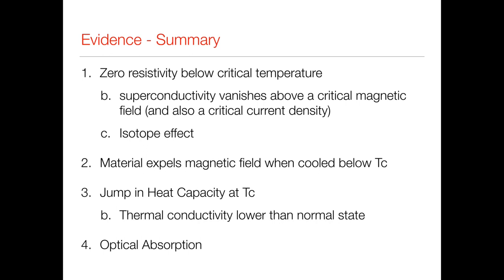A pretty telling piece of evidence is the isotope effect, the fact that the mass of the atoms seems to affect the transition temperature. We've got the Meissner effect, where the material expels the magnetic field when it's cooled below the critical temperature. We've got a jump in the heat capacity at the transition temperature. And something I haven't dwelt on, but if you look at the thermal conductivity, that's much lower in the superconducting state than you'd expect from the normal state. And then finally, there are the experiments on optical absorption and this somewhat anomalous effect in the microwave region. So in the next two sections, probably the second part of the first lecture and the first part of the second lecture, we will unpick these and try to see what science we can extract out of all these phenomena.